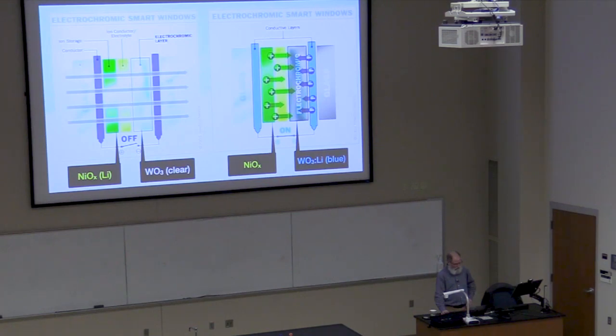That's the question. Once again, you have a piece of glass with a transparent conductor here, tin oxide, another piece of glass with a transparent conductor, and then on this side you have this electrochromic material, and this ion storage material, and some sort of polymer or ionic conductor in between. So this material could be like nickel oxide with a little lithium in it, and this material is always tungsten oxide, I should say. And when you flip the switch from off to on, these lithium ions move from here through there and form this blue tungsten oxide. And at the same time, of course, you get electrons flowing in the outer circuit. So this material is pretty amazing. It allows ions to move through it, but it doesn't conduct electricity. So anyway, you can turn your glass from clear to blue.